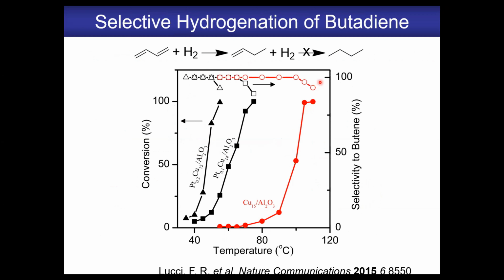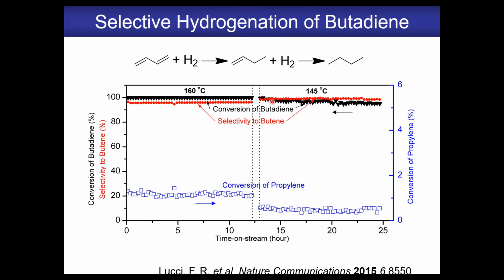And most importantly, you keep the high selectivity towards the butene that you want because of the copper doing most of the chemistry. And this is just showing for a day on stream in an industrial gas flow where you have a lot of propylene and you're trying to take out the butadiene. You see high selectivity to butene and you touch less than 1% of the propylene in the feedstock. So this looks like a really promising catalytic system.